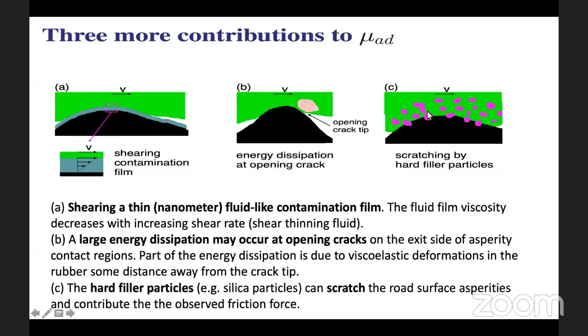And then there is also, as I told you before, that rubbers have different fillers in them, and these fillers can scratch the surface of the substrate. That wear process, the scratching and plowing mechanisms by the filler particles on the substrate, can also be a cause of energy release. So that can also contribute to friction in the area of real contact.